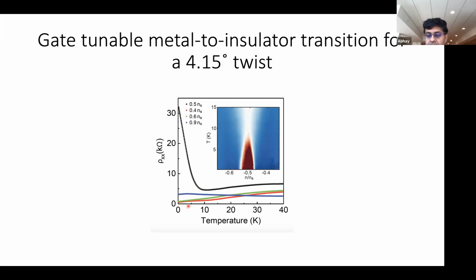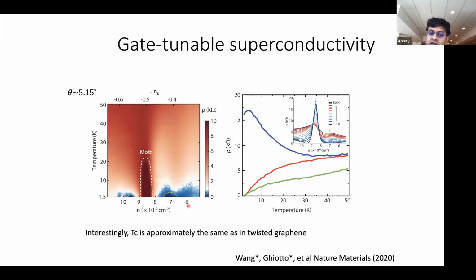And if you're away from this half filling point, then you have metallic behavior all the way down to the lowest temperatures. And for particular angles under particular conditions, which I don't want to go into detail, but I'm happy to if you have questions, when you dope away from that insulating half-filled position, we were able to actually observe zero resistance, although we would like to see a few more samples of this before we say a lot more about it. The maximum TC, quite interestingly, was quite similar to twisted bilayer graphene, which is sort of an interesting phenomenon.